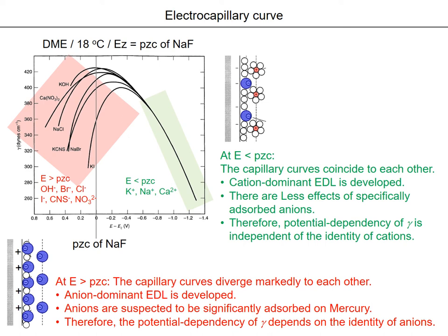Okay, here is the real data of the electrocapillary curve. The x-axis is the potential minus the point of zero charge of sodium fluoride, and the y-axis is gamma, or surface tension. The unit of surface tension is force per centimeter. Of course, the dropping mercury electrode was used as the working electrode, and the experimental temperature was 18 degrees Celsius. And also, we have tested several salts, like potassium iodide, sodium bromide, potassium CNS, sodium chloride, calcium nitrate, and potassium hydroxide.